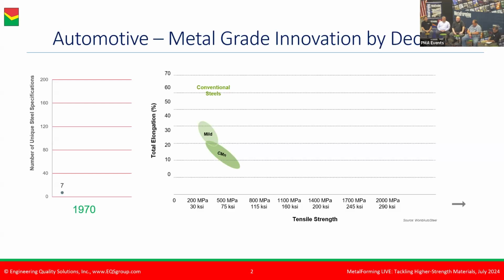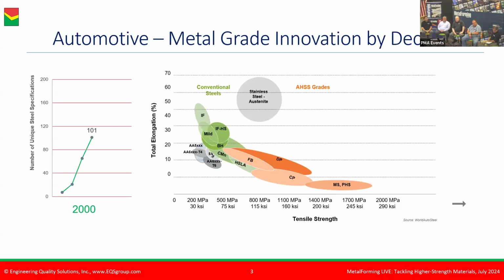Relative to the automotive industry, there were 7 unique sheet metal specifications where these 2 grade families came out of. I'm going to fast forward 30 years to the decade of the 2000s, where it's not anymore 7 unique automotive sheet steel specifications, but over 100 now. And we have a plethora of new grades in the steel family, that's when the first generation of advanced high strength steels were commercially released. But we also see automotive applications of sheet aluminum alloys as well as stainless alloys.